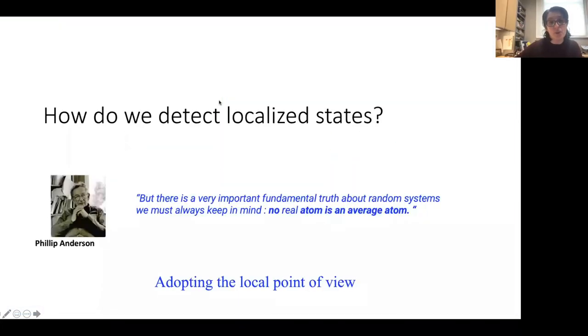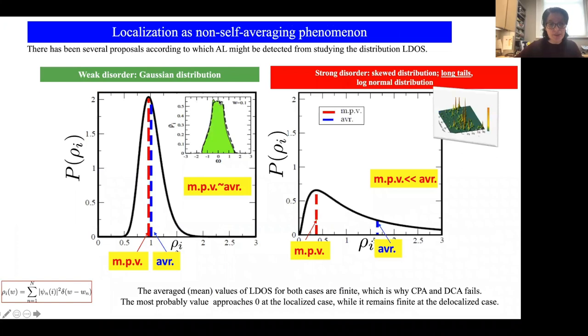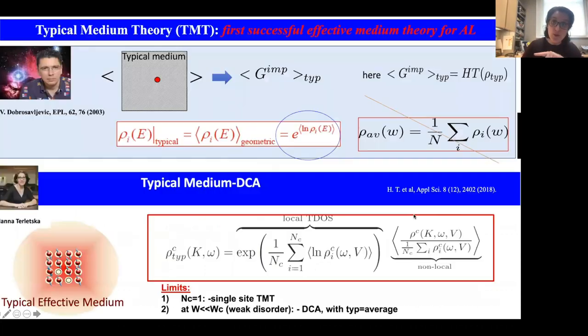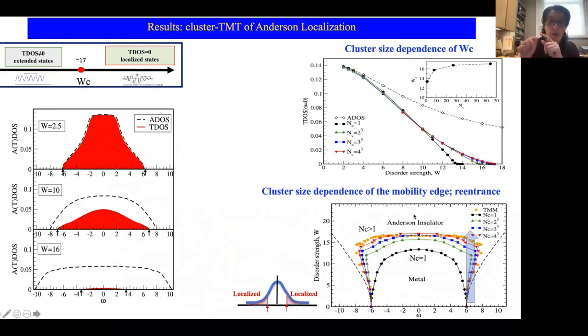I see. Very, very good question. By the way, I didn't mention this because I didn't have time, but this log normal distribution that I have shown you has actually been measured experimentally as well, by Ali Yazdani's group, where they look at the probability distribution function of the local density of states and how it changes with disorder. But back to your question, very good point.